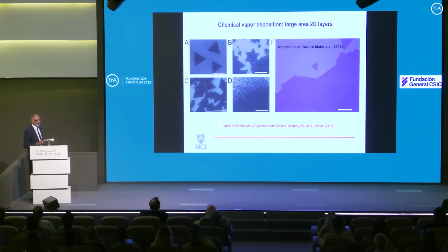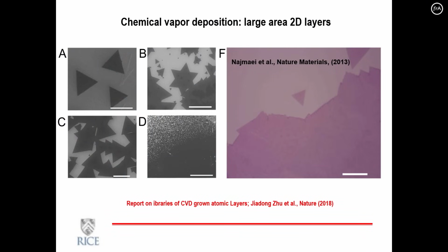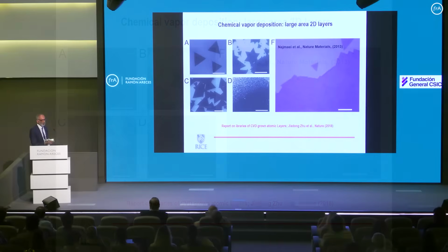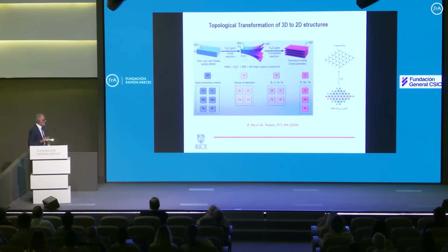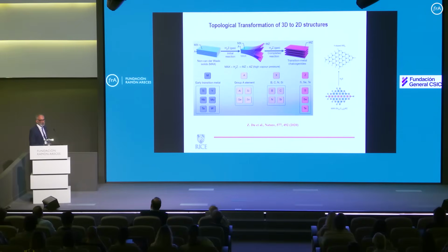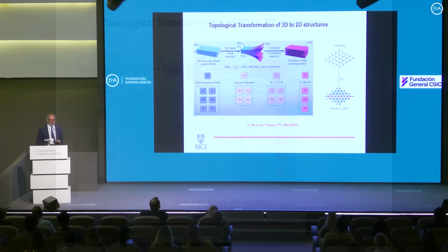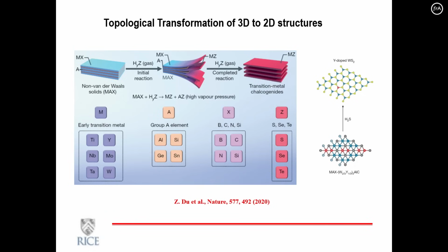You can also grow them now scalably over a very large area, or even by roll-to-roll manufacturing using vapor deposition processes. And again, there are many works in the literature that show that you can make very large area 2D material. Another way to make this would be to take a 3D material and convert it into 2D. Take a non-layered system, convert it into a layered system, and then remove layer by layer. So there are multiple ways that exist in today's literature that allow you to make these materials that are single unit thick, coming almost to the end of the thickness you can get to. You're almost looking at the frontier in terms of dimensions, in terms of thickness.